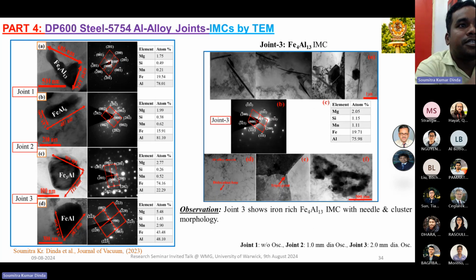But the interesting thing is for joint 3. In case of joint 3, we got some bigger, irregular sizes. Suppose this is a needle type of shape, and see the unit, 1 micron. This is more than 4 micron, and this is in nanometer. So this is the needle shape, hexagonal shape. Also, we can see the cluster or garland type of intermetallic formed in case of joint 3. We did the EDAX study and the SAD pattern study, and we found this type of intermetallic is Fe4Al13. And our literature suggests that aluminum bearing intermetallics are more brittle compared to iron bearing intermetallics. This one is the aluminum bearing intermetallic. That is the reason we are getting very poor mechanical property for this joint 3.